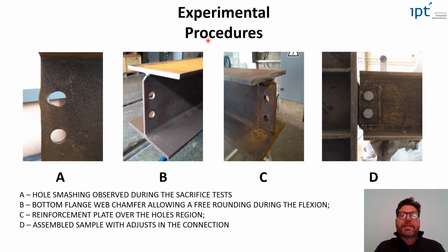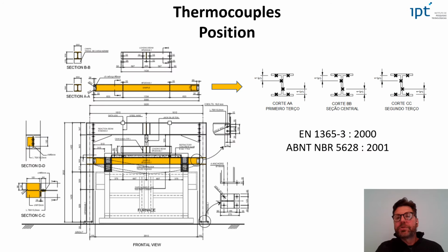Well, before running the tests themselves, we did two sacrifice tests to see how the furnace would behave, as well as the beams, and it was observed that some limit states were reached in the connection part of the structure. By the way, it is important to say that the behavior of the connection was not the focus of this research. So for the official tests, we provided reinforcements on the web, as you can see here, and a small chamfer at the bottom flange to allow free rotation during the bending. And we did it to all 8 samples.